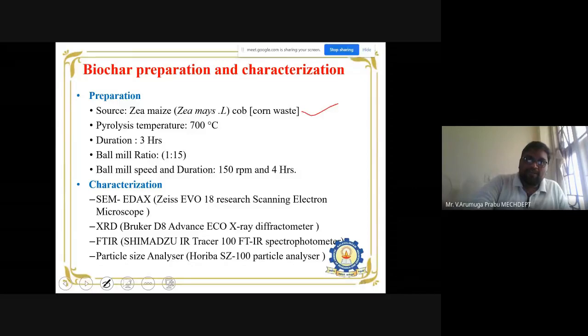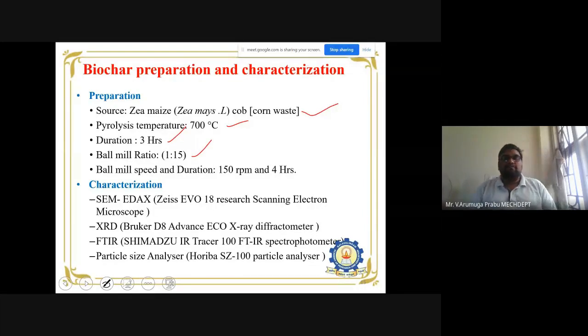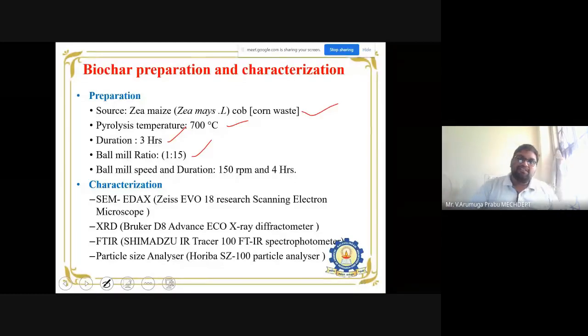The source is corn waste, and then the pyrolysis temperature. This temperature normally should be varied from 500 to 700. You can take 500, you can take 300, depending on your waste material. This 700 is suitable for corn cob. In some cases, 700 will not produce your biochar. So depending on the material, the temperature will vary from 300 to 700. The duration of burning is normally 3 hours in a closed confined environment where there is a complete absence of oxygen. After the content is obtained, it is subjected to ball milling, normally in the ratio of 1:15 to obtain a smooth fine powder form. The ball mill speed and the duration in hours also vary depending on your material.